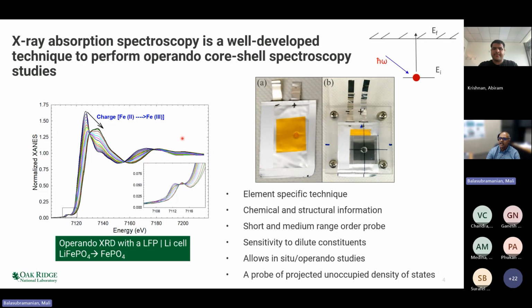Here is an example of LFP, where the lithium iron phosphate is converted to iron phosphate and monitored operando as the cycling is performed. These can be done by specialized cells that are manufactured to study them during operating conditions. Here is an example of a cell that we commonly use. It's a pouch-like cell, and the stack pressure is maintained by using a beryllium window.